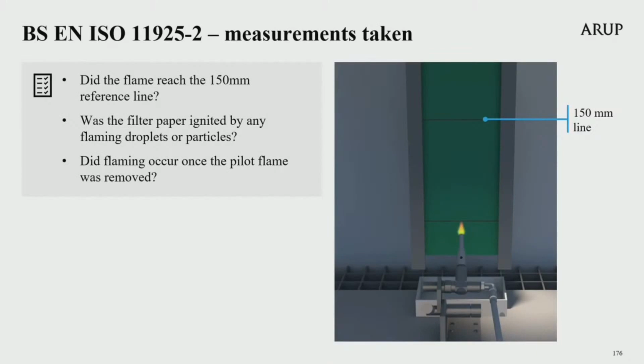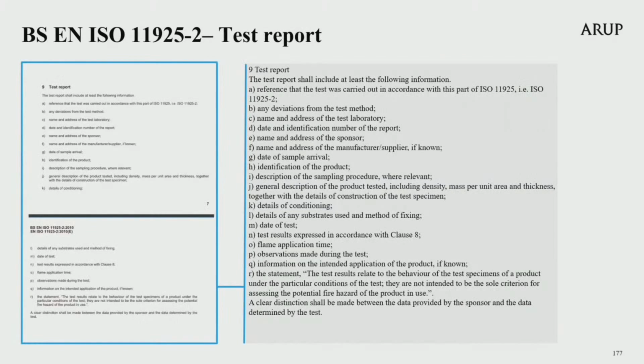Regarding the results, first it is noted whether the flame extent reaches the 150 millimetre line marked on the screen. Also, the presence of any flaming on the specimen once the pilot flame is removed is recorded. The test report must identify whether any flaming debris falling from the specimen ignites the filter paper. On the slide now are the requirements for the test report.